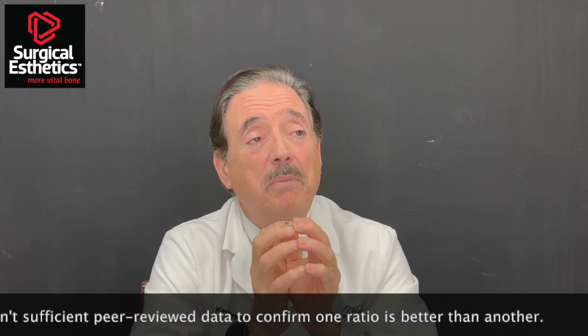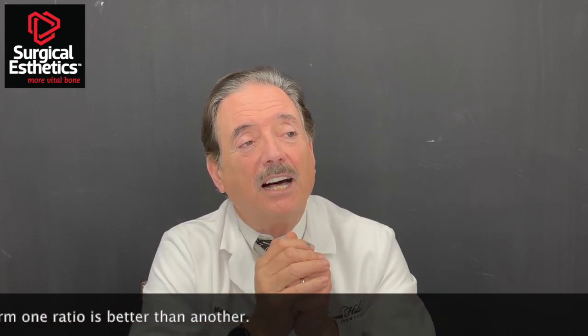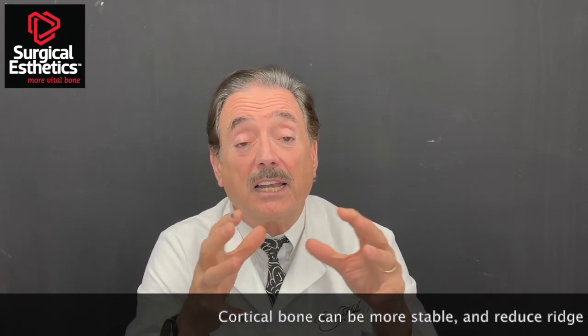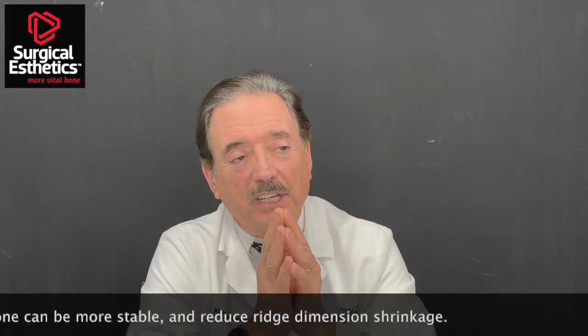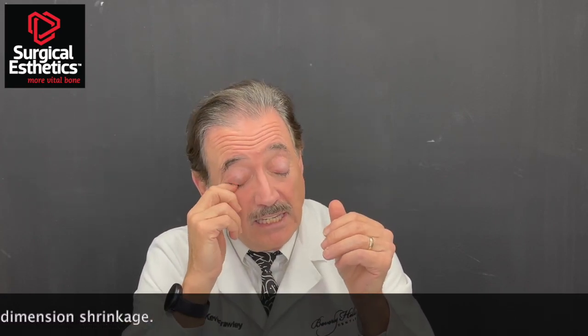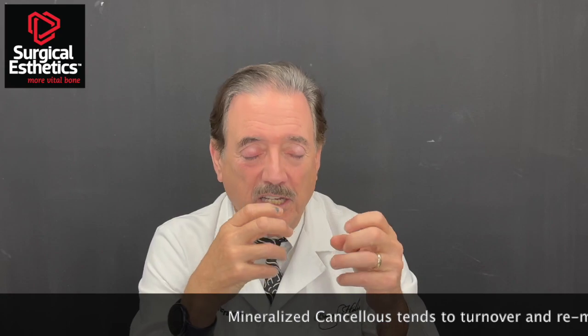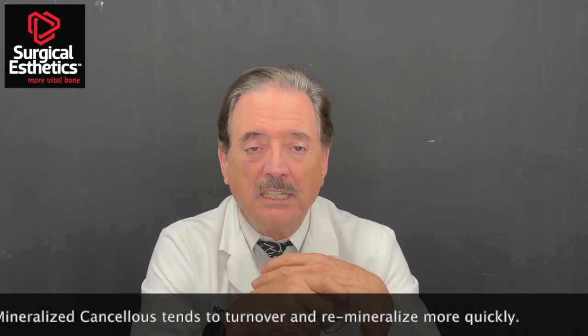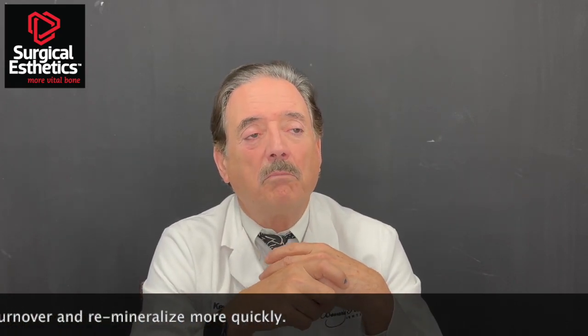So the benefit of the mix is that with the cortical particles, you'll get a more stable clot and less chance that you're going to get some shrinkage. The straight mineralized will heal faster because it'll turn over faster and create the patient's own bone and vital bone. But the cortical particles will help kind of hold the space.